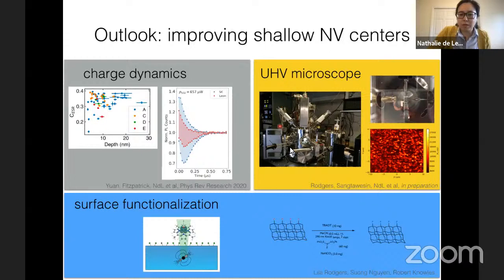I'll also mention a couple of the chemistry efforts just very briefly. One of the things that we've been working on intensively over the last couple of years is trying to interrogate NV centers in ultra high vacuum conditions. As I alluded to in the brief first Q&A section, you're very sensitive to surface contaminants. So far, nobody has really looked at a contamination-free surface because you actually need ultra high vacuum conditions to do that. So what we have is a surface preparation and chemistry chamber where we can really prepare these pristine surfaces, and then an attached UHV cryogenic confocal microscope where we can look at NV centers without breaking vacuum.